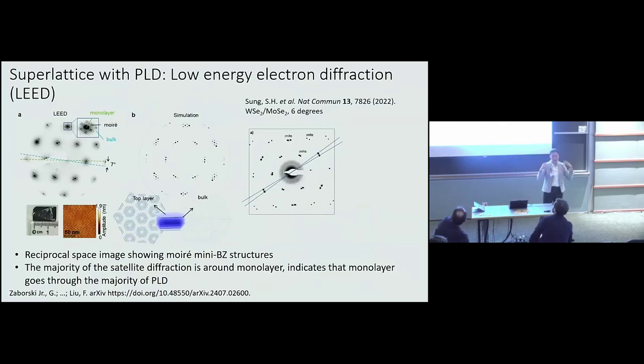If you have just two monolayers isolated from each other, without any periodic lattice distortion, then you would expect their electron diffraction patterns to just superimpose the diffraction patterns of the two monolayers. But if we have this periodic lattice distortion that creates a longer periodic modulation of the crystal lattice structure, we would see satellite peaks around the main bright peaks, and that is what we see here in this low energy electron diffraction. There's monolayer twist, monolayer on bulk. We have a monolayer peak and a bulk peak, and these beautiful moiré superlattice peaks.